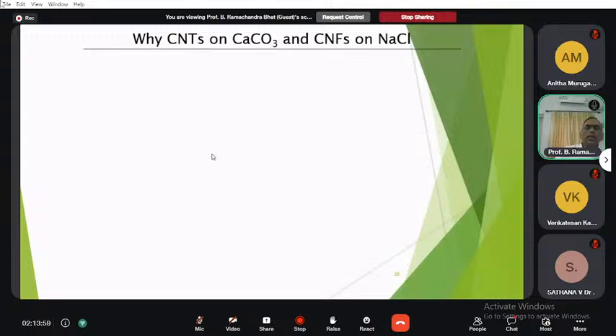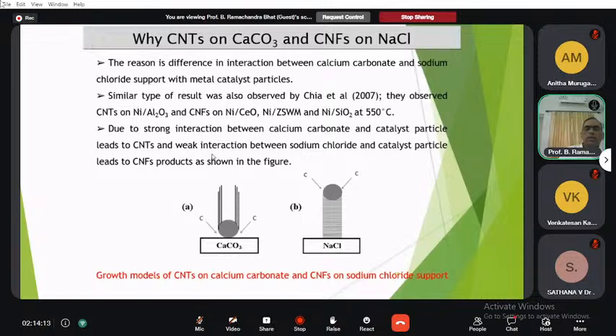And see why this CNT is obtained when we have taken calcium carbonate as a support, and why the CNF is obtained on sodium chloride as a support. The reason is very simple. It is nothing but the interaction between the metal nanoparticle and the substrate. In the case of the metal nanoparticle with calcium carbonate, this interaction is very strong, and that's the reason why the carbon is precipitating out as a tube, because there is a strong interaction between the metal nanoparticle and the calcium carbonate substrate.